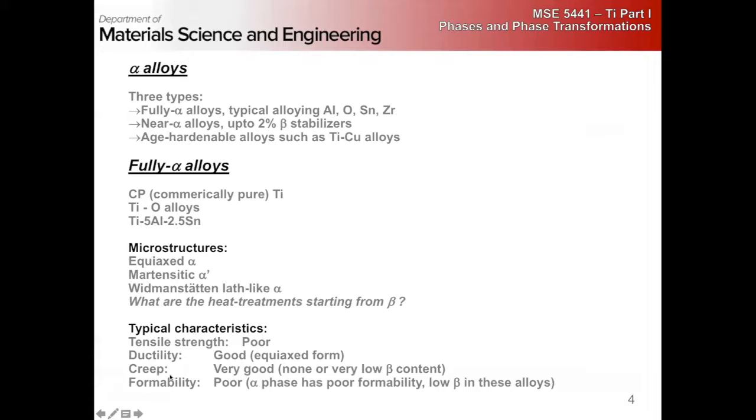So why would they do poorly in formability? Right? It's just going to be the temperature dependence of slip, right? Accommodating C-axis deformation. So if you deform these things fast and at relatively low temperatures, you're going to form a lot of twins or have to activate very difficult C plus A slip.